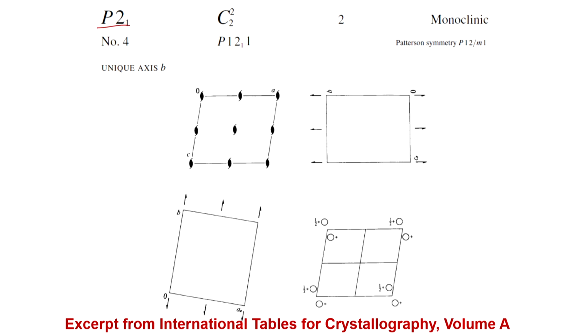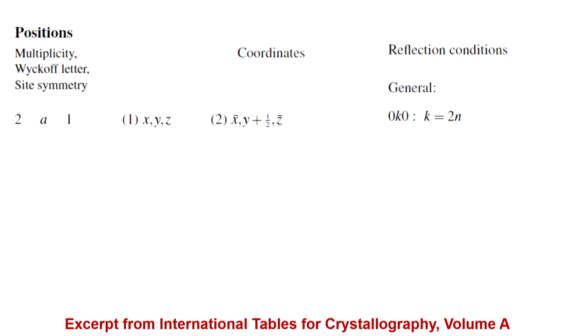Now, this space group, what we have done here if you recall, in a primitive monoclinic lattice, one has added two-fold screw axis. So, two-fold screw axes are at the corners, at the centers of the edges and in the center of the cell, and this is how the motifs, or the general positions, get rotated around by the screw axis at all the four corners of the cell. And now we just directly come to what are the general positions in this.